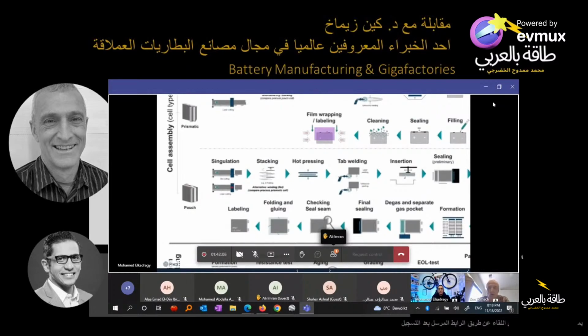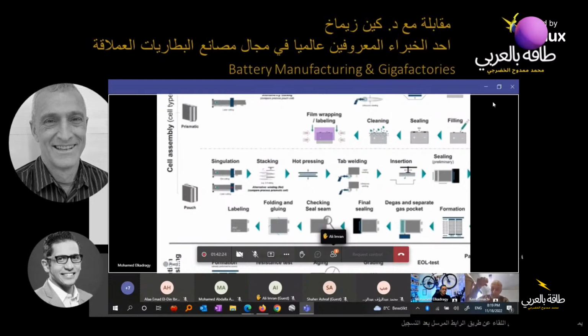Okay. So after you've made this jelly roll, which hopefully while you're handling it, sometimes you hot press it to try and get it to all stick together a little bit, but you can't use too high temperature, you can't use too low temperature, depends what separator you're using, it's very complex. Then you insert it either into a pouch for a pouch cell or into a can, meaning usually an aluminum can. You might need to weld it to a lid first. It depends on your design, and then you need to seal it. In a prismatic cell, you're usually laser welding your lid to around the rim of the can, and if it's a pouch you're doing a heat seal.